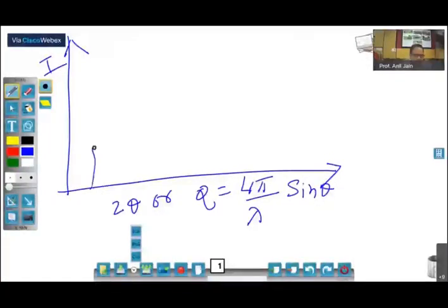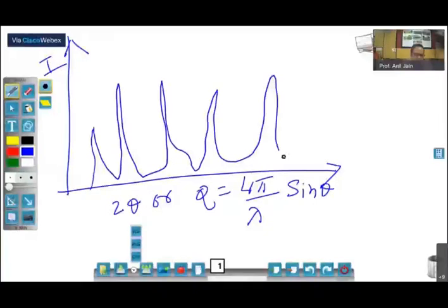So you get something like this kind of pattern. Now, the idea is to get the information from this powder diffraction pattern. And the idea of Rietveld refinement is that you try to calculate the full pattern depending on the model you have, and then try to minimize the difference between observed and calculated pattern.